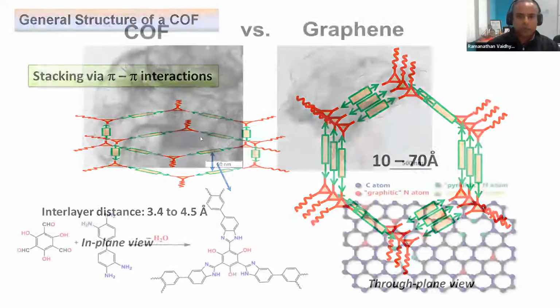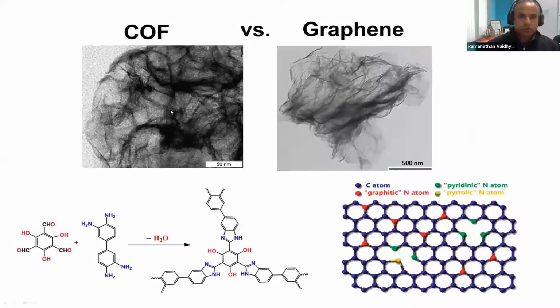I will draw your attention to another interesting thing. I'm showing here a high resolution TEM image of a COF, and I am comparing it to graphene. You can see a lot of similarity, from which we can make a few important statements. One is that COFs are nanomaterials, very similar to graphene. Also, it's important to realize that even in these small, flaky structures, there are several layers of this graphitic material buried, which is very interesting.